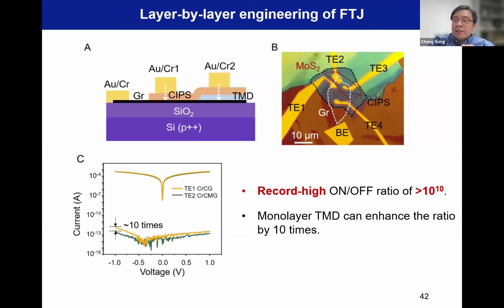The third one is, you can see FTJ is based on the ferroelectric modulation of band alignment between the three layers. So you can see here in the CIPS graphene interface, no Fermi level pinning. But traditionally, you have oxide, you have a metal semiconductor or metal insulator system. You always have the metal induced gap states and the related Fermi level pinning. No matter whether it is hard Fermi level pinning or partial Fermi level pinning, you have Fermi level pinning. So that will weaken or even nullify the ferroelectric control of the band alignment. But in the CIPS graphene interface, you don't have such an issue.